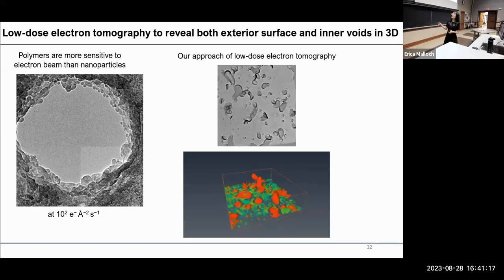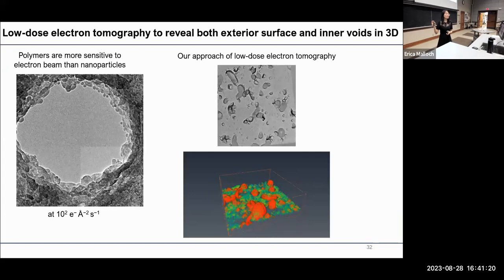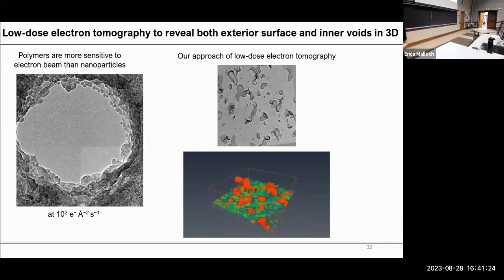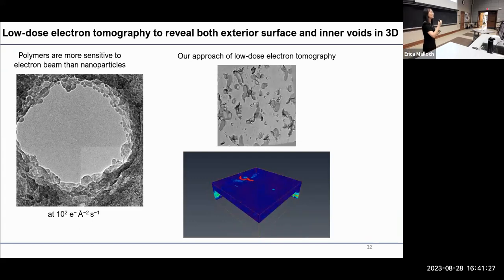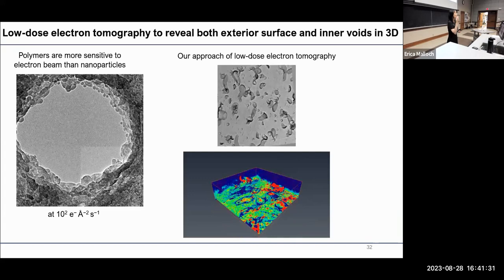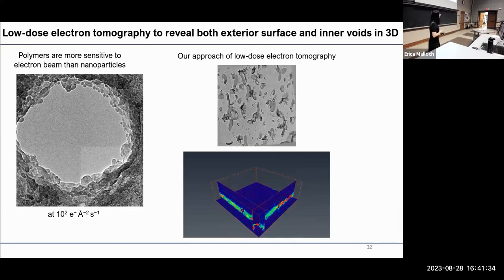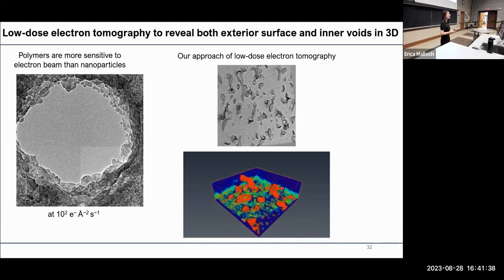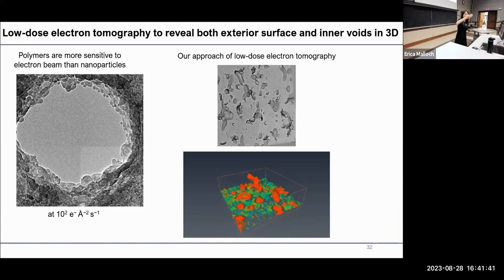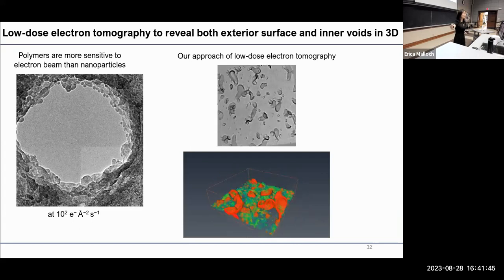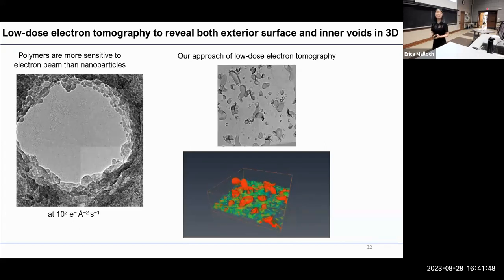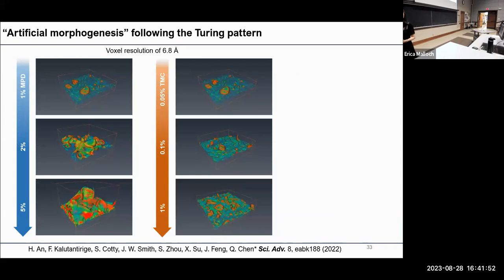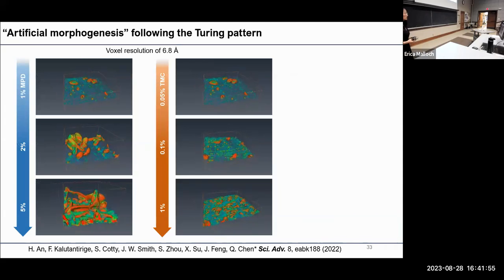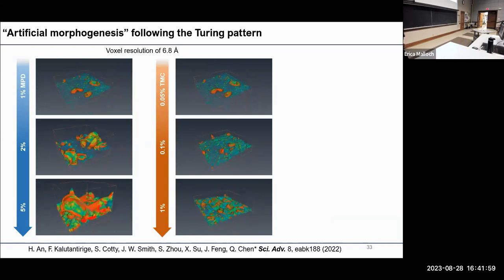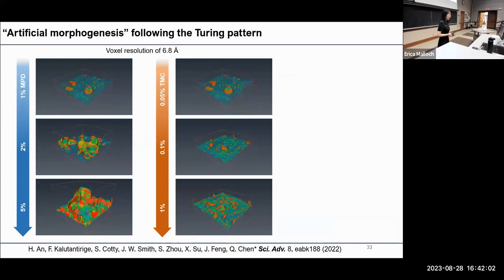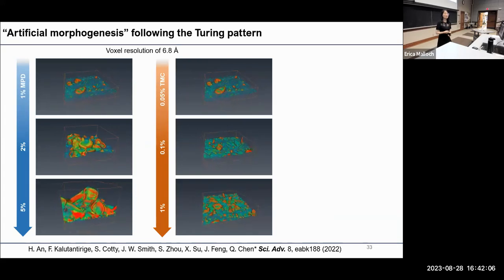This is a raw TEM tilt series. If you look at this series really carefully, your brain is actually a wonderful computer. You can already reconstruct to realize that each crumple, each feature, indeed protrudes in the z-direction. And below in this computerized reconstruction, you can clearly see the nanoscale features. More importantly, if you follow the slices, you can recognize they have nanoscale voids embedded in this membrane too. That's what we can resolve. We can apply this method to a collection of membranes synthesized at different conditions. This is what we get, consistently at a voxel size smaller than a nanometer. And based on those electron tomographs, we actually have two discoveries.